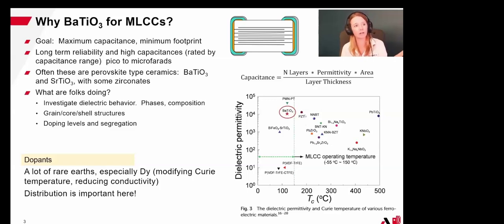Now, if we think about our capacitance, that's going to be a function of how many layers we have, the permittivity, the area, and the layer thickness. Here in this figure, we have permittivity over Curie temperature. And the Curie temperature is where we're going to have a ferroelectric regime and a paraelectric regime. The MLCCs are typically operating within this -55 to 150 Celsius operating temperature. And really what we want to do is have our Curie temperature match our typical operating temperatures or room temperature for a lot of electronics or a little bit higher.